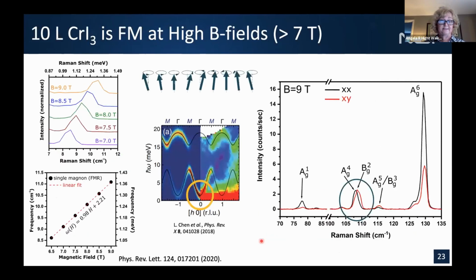So of course, what we learned was if we apply our magnetic field, we can split magnons and see them. So we turned up that magnetic field to 9 Tesla, and we saw some interesting things. First, we saw a low frequency feature that turned out to have already been seen by our Ohio State colleagues as a ferromagnetic resonance. Yes, Raman can see FMR.